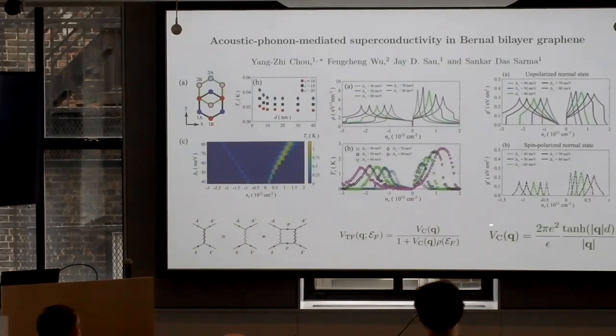Now, first, there is a screening effect just coming from the gates. You have gates. So this is just the undergraduate image charge effect and you can derive this formula because there are many image charges. There are 2 gates. And immediately you find the actual Coulomb interaction 1 over Q is suppressed by tanh(|q|d). All our calculations in bilayer graphene and in TMDs include this, our Coulomb interaction, because there are always gates. But this gives rise to very small mu star. So this doesn't explain the experiment.